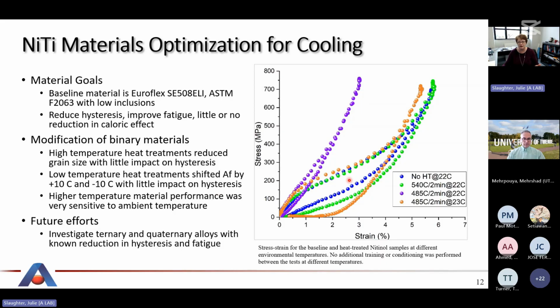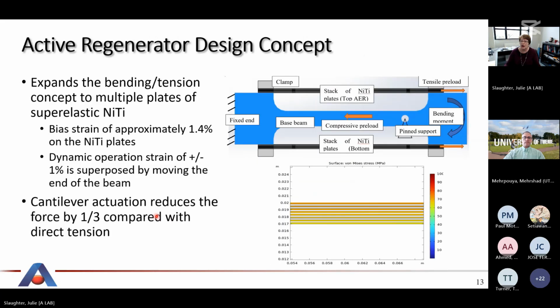If you're using it for cooling, you want that austenite finish temperature to be below the temperature you want to operate at. So this would not be suitable for room temperature cooling, but it is suitable for higher temperature applications. So just something to keep in mind. We are going to start moving to ternary and quaternary alloys to reduce the hysteresis and fatigue. So that's really where we are with our materials effort.